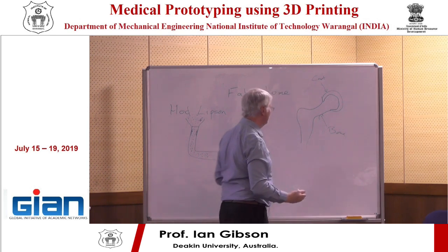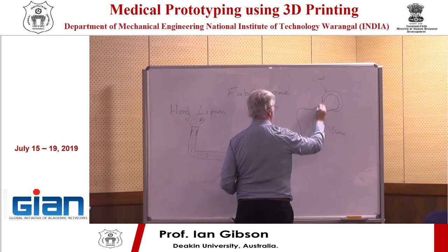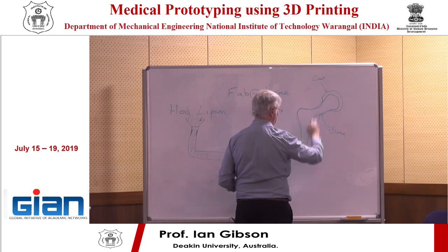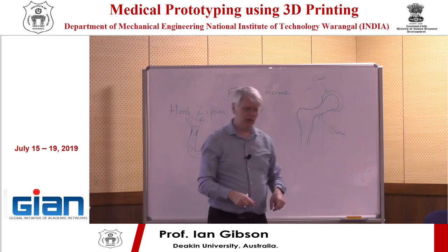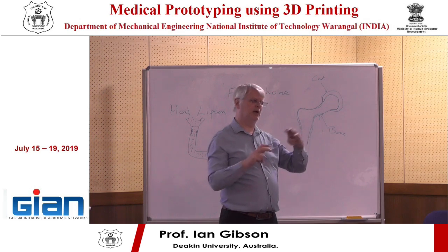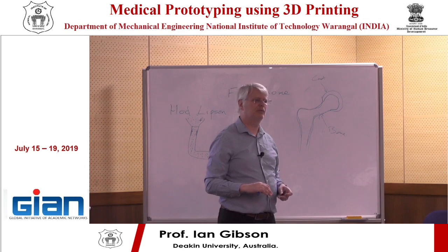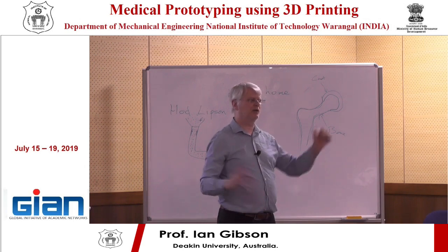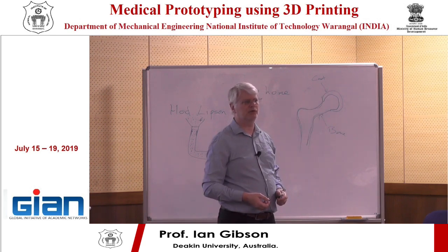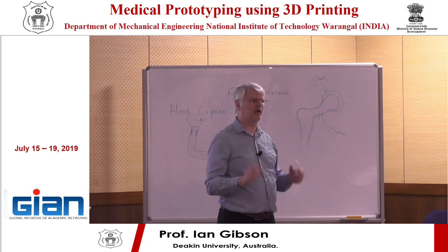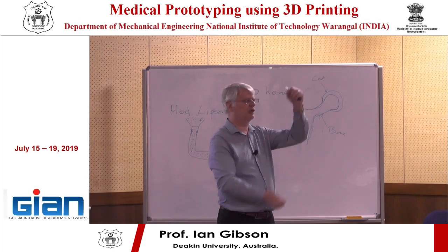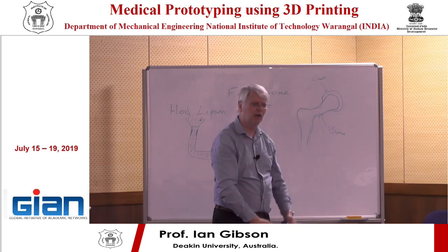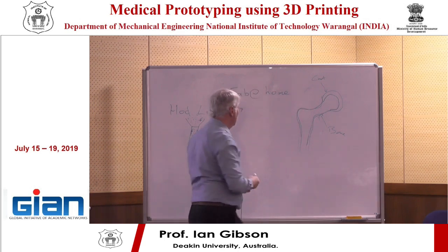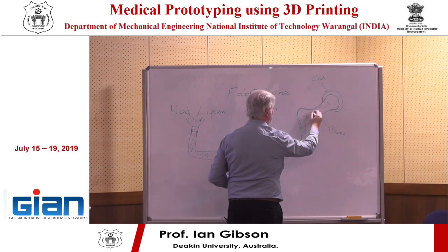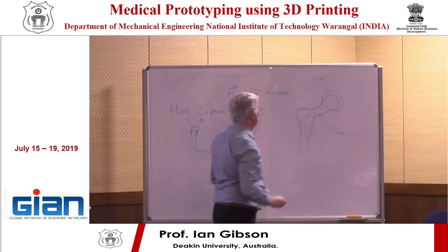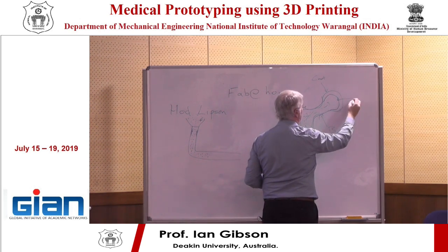One could also then subdivide that: you would have cortical bone with trabecular structure. People are playing around in bioreactors with the bone, and then actually putting mechanical stress on the cells. Some use inductive fields, some do mechanical compression of the cellular structures. There's quite a lot of evidence to suggest that's how trabeculae actually form. If you push the cells in a particular direction, they react by growing along that direction. Okay? And then you've got cancellous bone, spongy bone inside here. Certainly around this region, you've got an interface.